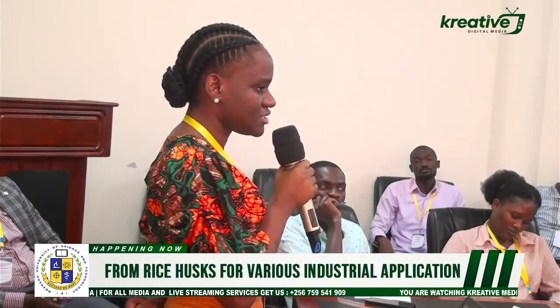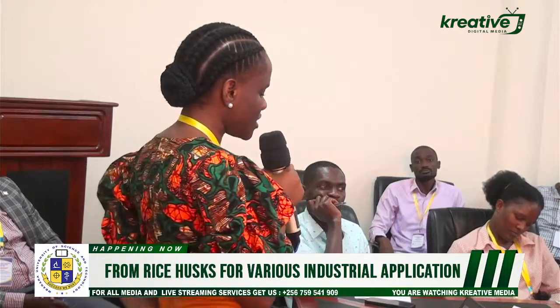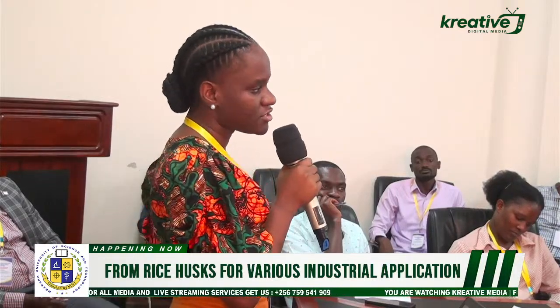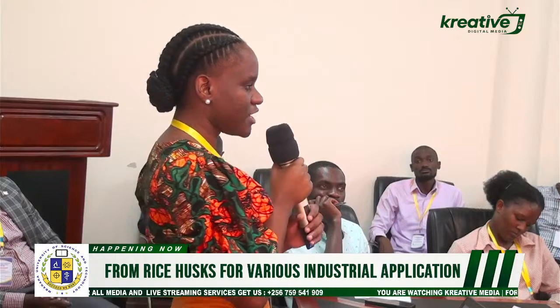Then my synthesis will involve burning the rice husks at 600 degrees Celsius in an electric furnace for 6 hours to form ash. This ash will be treated with sodium hydroxide with magnetic stirring for 1 hour, and then the residue will be reacted with sulfuric acid to form the Bio-Silica nanoparticles.